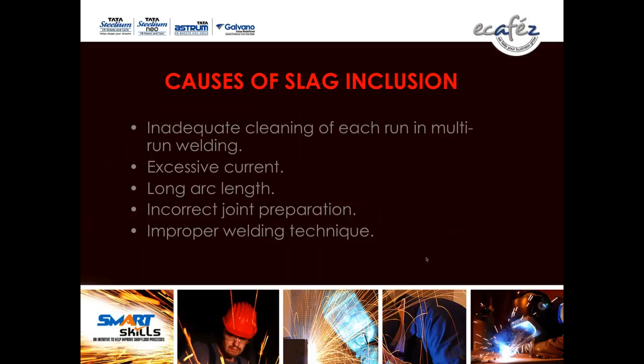So these four, crack, lack of fusion, lack of penetration and undercut, are the linear welding defects and should not be permitted in welding. Next, causes of slag inclusion. Inadequate cleaning of each run in multi-run technique. Excessive current, long arc length, incorrect joint preparation, improper welding technique are the causes of slag inclusion. Actually, the welder is solely responsible for slag inclusion, nobody else.